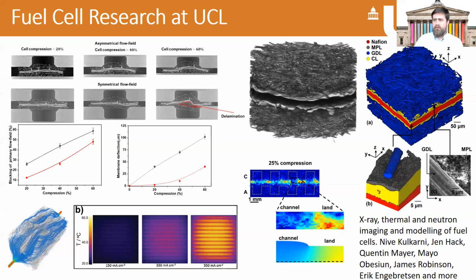And so a lot of the research is focused on that oxygen side. When you look at methanol as a fuel, you've got to look at both sides, and try to improve the anode and the cathode side in terms of the catalysis. There's also an issue because methanol is liquid. It can more easily transfer through the structure of the Nafion membrane along with the water. So you get this crossover issue as well, which can poison the other side of the fuel cell and also lower your operating voltage.